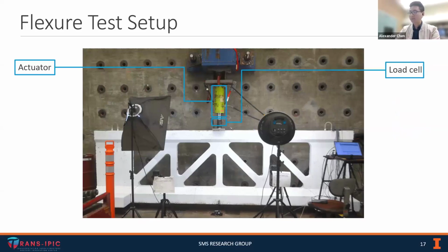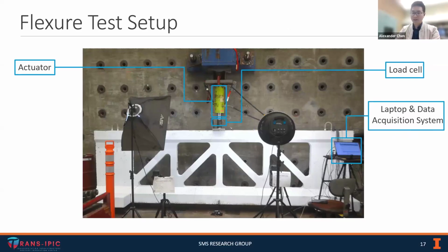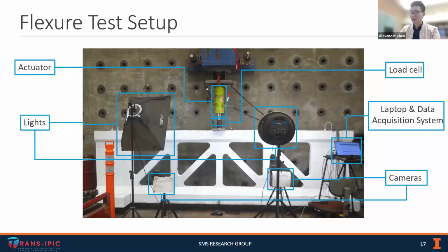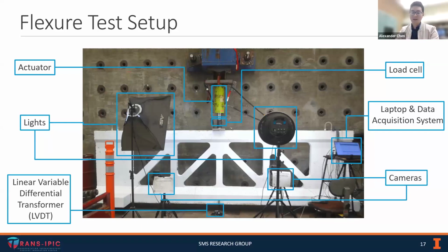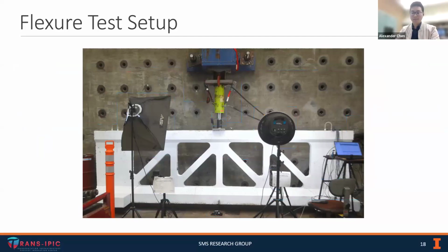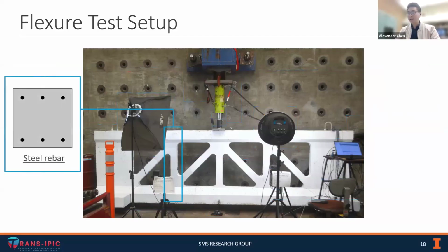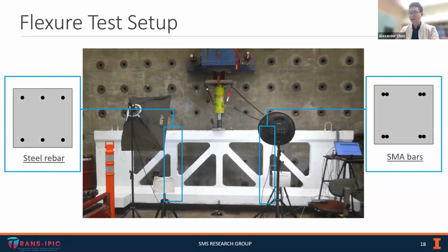We have an actuator at the top, a load cell between the actuator and the test specimen to measure the applied load, a laptop and a data acquisition system to record all the data. We have 2 lights, one for monitoring each specimen, as well as 2 cameras, one to monitor each vertical member of the test specimen. And we also have an LVDT to measure the vertical displacements of the test specimen. So in this current orientation, the steel member is on the left-hand side, and the member that has the SMA bars is on the right-hand side.